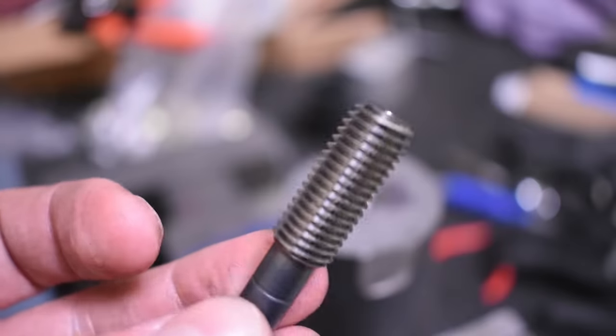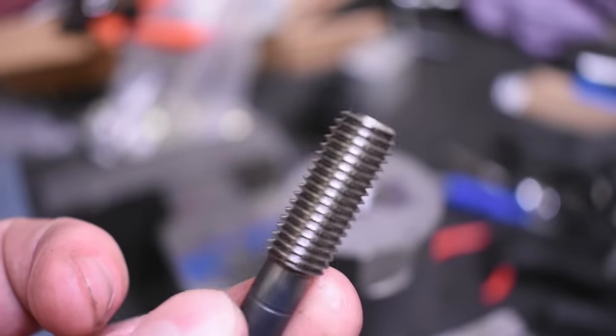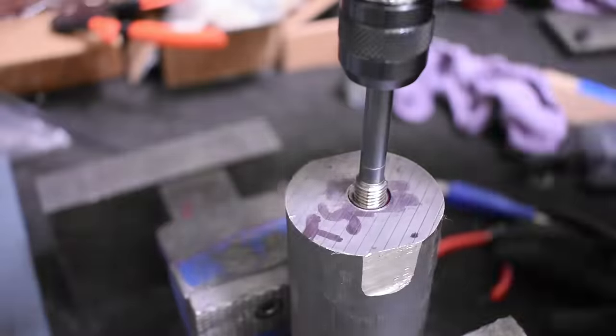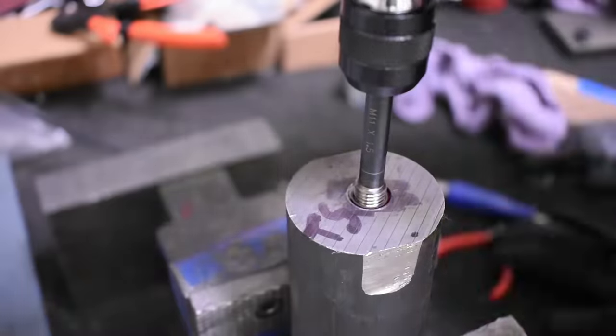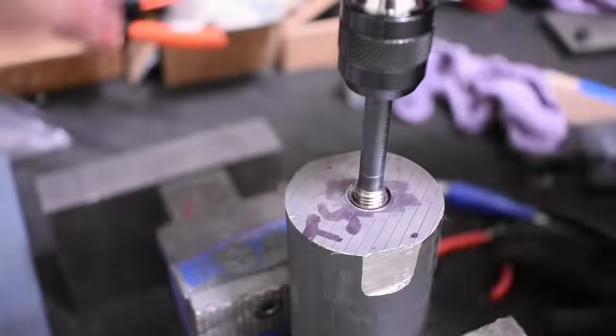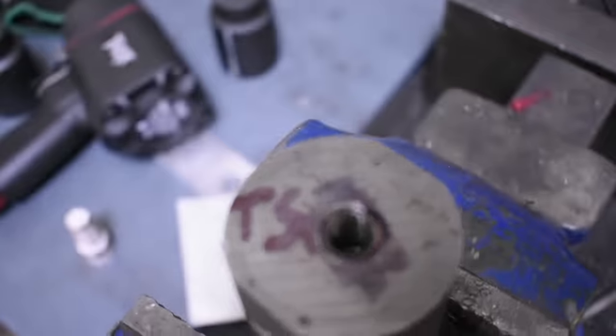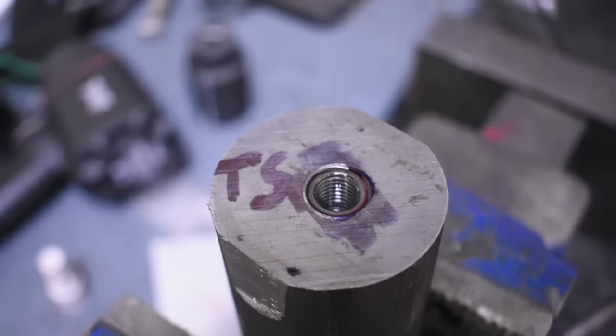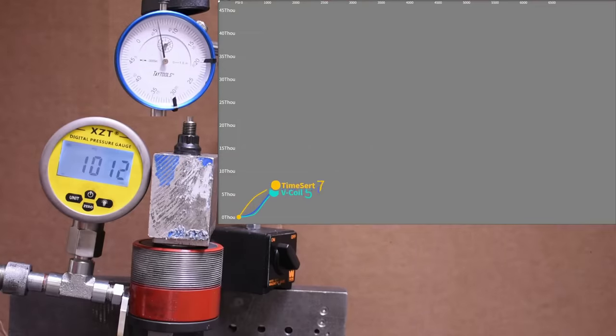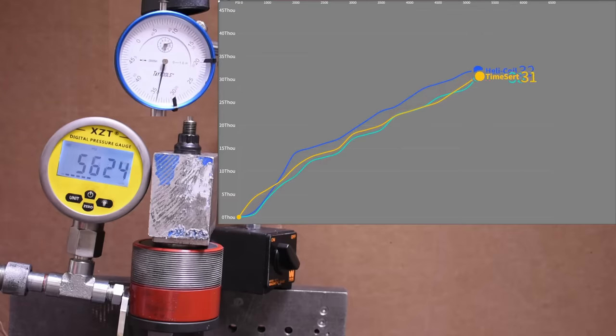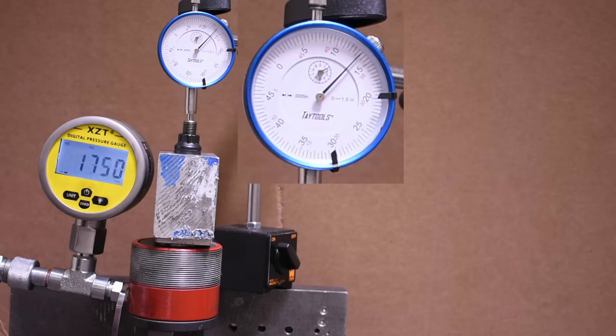Their install tool is rather unique and has these eccentric cuts on it, and it gets some oil first and finishes the threads in the insert, leaving a solid insert that you can thread things in and out of. You can definitely feel it snug up and start to work at the bottom of the insert. The Time-Sert shows you some pretty minor stretch all said and done, but ultimately similar like the others to the L19's bolt strength between that 3600 and 6500 PSI. Here's the Time-Sert once things are really ramped up.